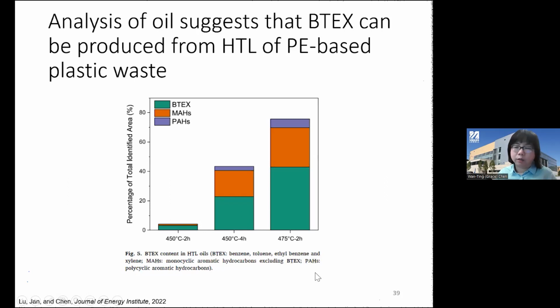In this case, we found that by fine tuning the reaction condition, we'll be able to generate this so-called BTEX. It stands for benzene, toluene, ethylbenzene, and xylene. They are valuable aromatics, these BTEX single or mono ring aromatics. However, if we have multi aromatics or poly aromatics, then that's not good. Then it means they become char, and PAHs are actually hazardous chemicals. So we want to follow up with studies. We want to know how we can generate more BTEX instead of these PAHs in this case.